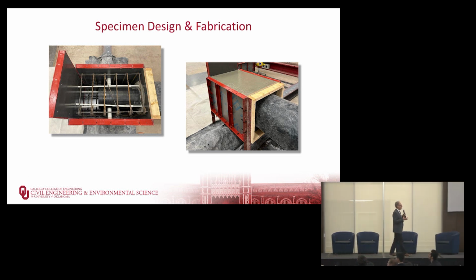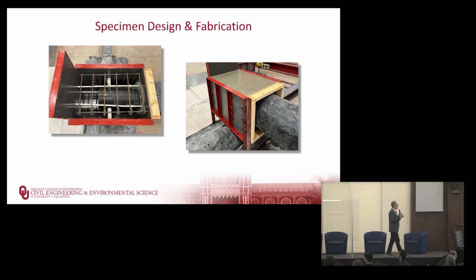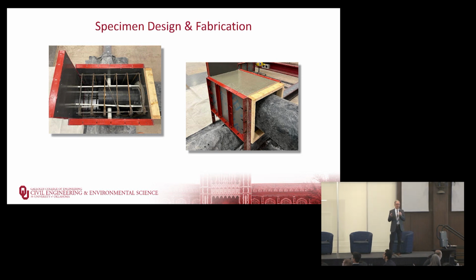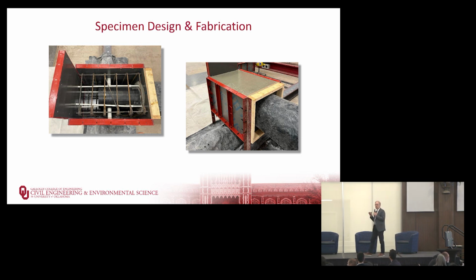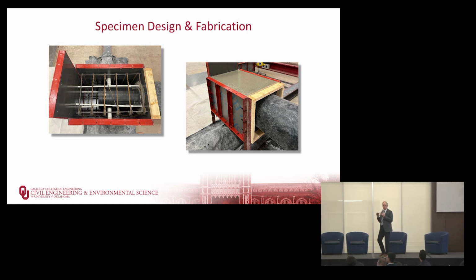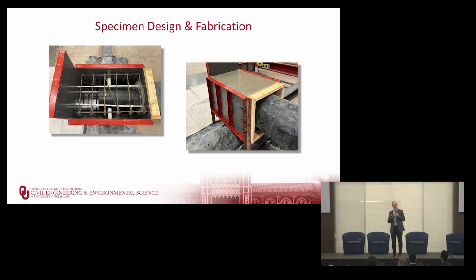Because we only have a 5-ton crane at Fears, with the loading head installed on the top, it would have weighed too much. So first we had to move it, we had to lay it over, get it in the test frame, and then cast the loading stub at the top. We applied our nominal axial load using pre-stressing. We just use axial pre-stressing, 4 half-inch diameter special strands, cast within the column that we would pre-stress to get our 80 kip axial load that will be constant during the cyclic testing. And that's what those white tubes are.